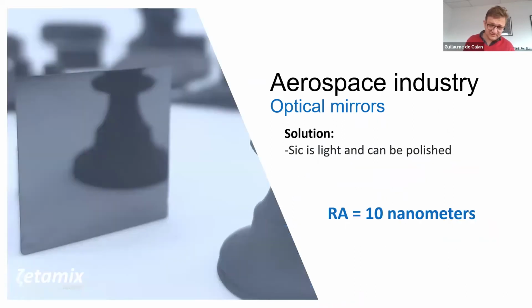And really silicon carbide ticks all of these boxes, and that's why we're using it. It's very lightweight, it's very stiff, it's very strong, and it can be polished to very, very low surface roughness. Typically here you have a small part that we did when we did our first prints with silicon carbide. After printing, debinding, sintering, we did some polishing, and we went down to a surface roughness of 10 nanometers, which is really excellent and good enough to make afterward metallization and to make a mirror out of it. So that's the first application.